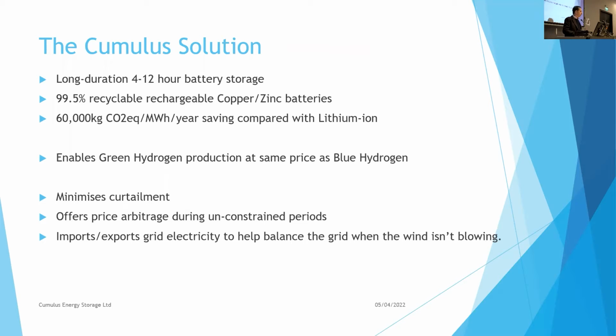Well, firstly, we're talking here about a longer duration energy storage system. We're talking about 4 to 12 hours charge and discharge times, which is really, really helpful when you want to actually tackle some of the curtailment issue. We're also talking about a very green solution. We've got abundant materials, abundant metals that are used. So not just the zinc and the copper, but also aluminium and stainless steel are the fundamental materials in the electrodes. And then even our electrolyte, which is a liquid, is biodegradable. So it is a very clean green solution, and it's very recyclable.